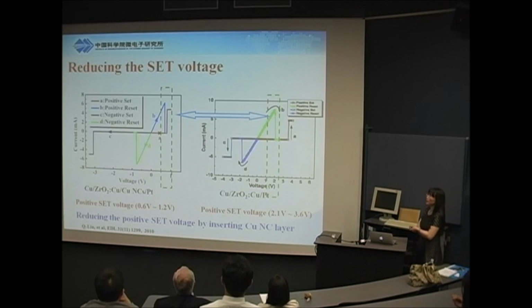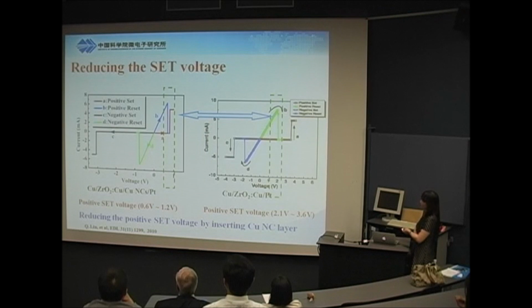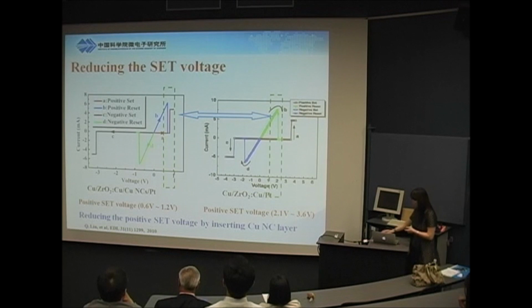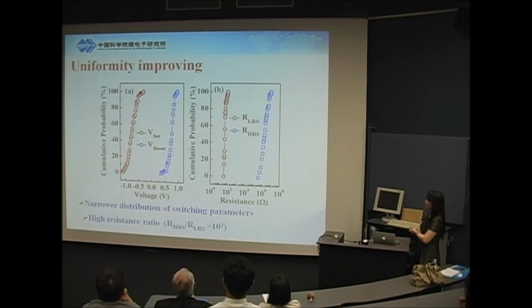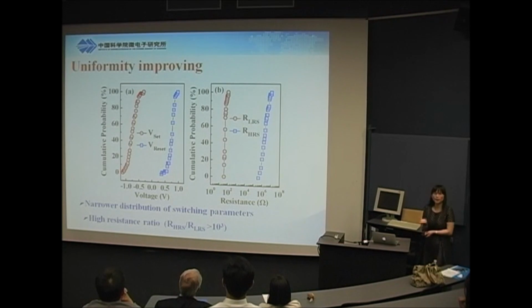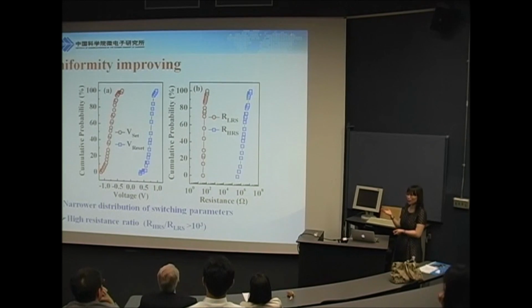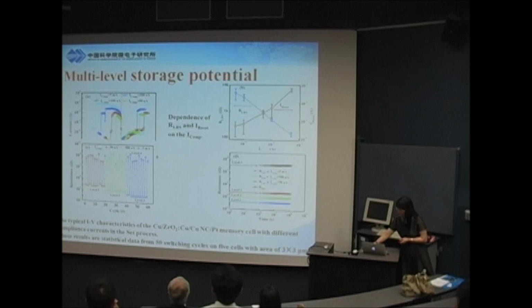Next, we can see the performance of the device. We compare the device with inserted nanocrystals and without. This is the inserted nanocrystal device. Its set voltage is reduced largely. Also, the distribution is not so large. Here is the difference. Also, you can see the parameters have a very narrow distribution. This way works. It really improves the performance of the device. But at this moment, you can still see the filament really formed around this nanocrystal. Next, we also demonstrated another performance: even for multiple levels, you can see 4 levels in a single cell. Even the cycling is very good.